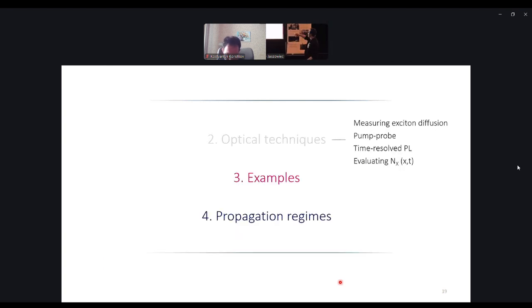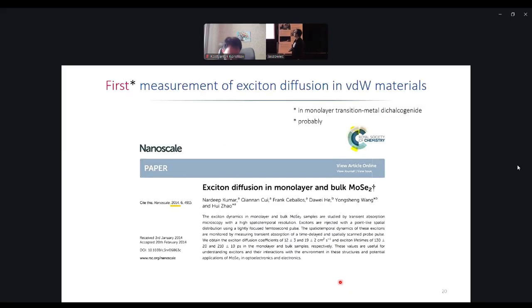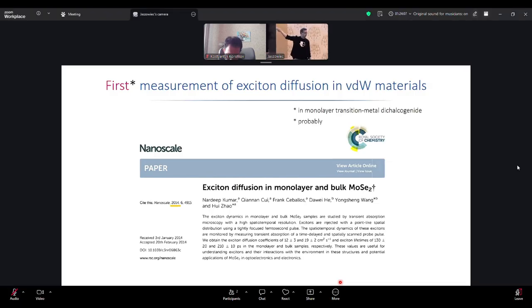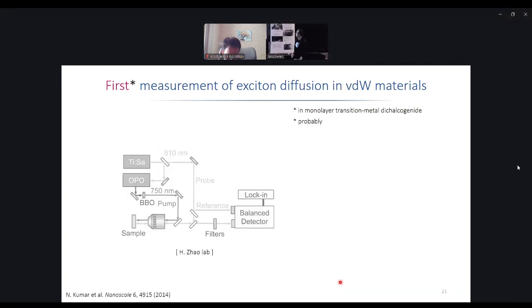So with this, we're done with the first part about measuring exciton diffusion: pump probe, time resolved luminescence, our techniques of use, and then the evaluation of exciton density at the position x and time t is the relevant quantity. Now to the examples. The first one is for van der Waals materials, because the other materials you go back decades ago. This paper is about exciton diffusion in monolayer bulk MoSe2, where people use the pump probe setup. So this is a typical way how it can be done.